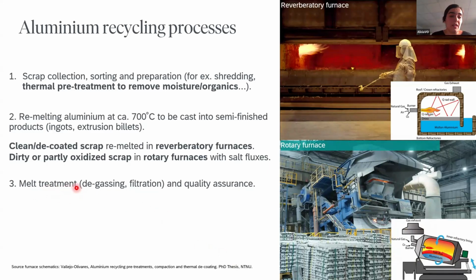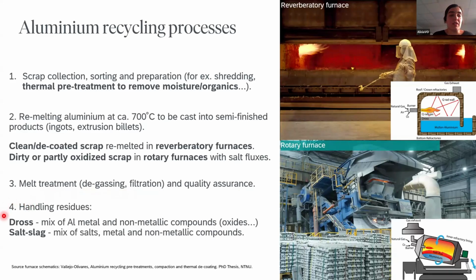Then the melt treatment steps can include de-gassing with argon gas to remove the non-metallic contamination like oxides and the hydrogen, and filtration. And then finally handling the residues that, depending on the route, will be dross in this case or a product called salt slag, salt cake or salt slag in these other routes. In Europe, of course, landfill is forbidden and there are processes to treat these waste products and recycle them back into the process or into other applications. For example, some of the oxides from the salt slag can be used for construction.